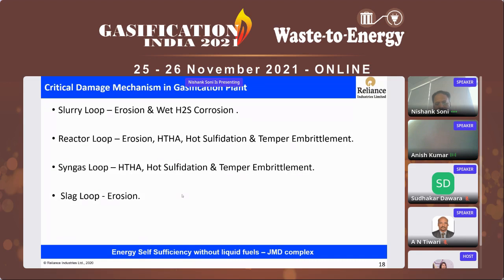As per the respective service conditions and methodology used, loop-wise specific damage mechanisms are taken here against each corrosion loop. For the slurry loop, the presence of solid particles in the semi-liquid slurry and the high velocity of the slurry lead to corrosion damage. Other chemically active elements like sulfur also change to sulfide, leading to further degradation. This may cause significant erosion as well as wet H2S corrosion.